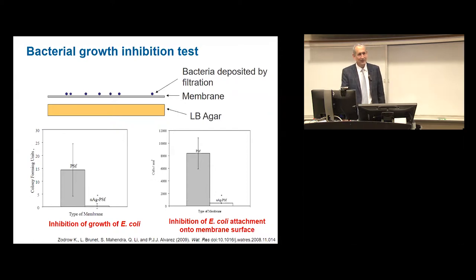But more interestingly, we took membrane coupons and dipped them in bacterial suspension, left them there for a while, took them out, washed them, stained them with DAPI, and looked at them in the microscope. And as you can see here, there was hardly any attachment of bacteria to the silver impregnated membrane because, for one thing, silver nanoparticles release silver ions, which are the critical effector of the antimicrobial activity of nanoparticles. I don't have time to show you that, but that's in a Nano Letters paper. The point here is that bacteria sense this silver, and most likely it exerts negative chemotaxis. So they go away. This discourages attachment, which is important.